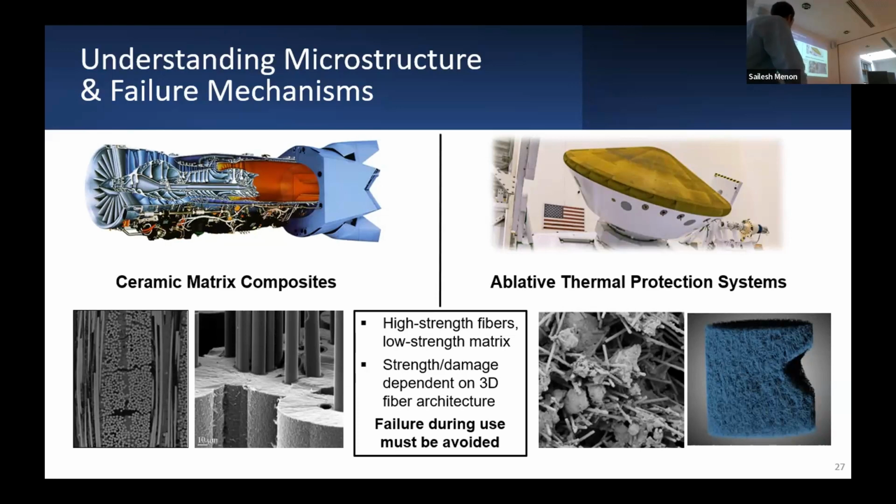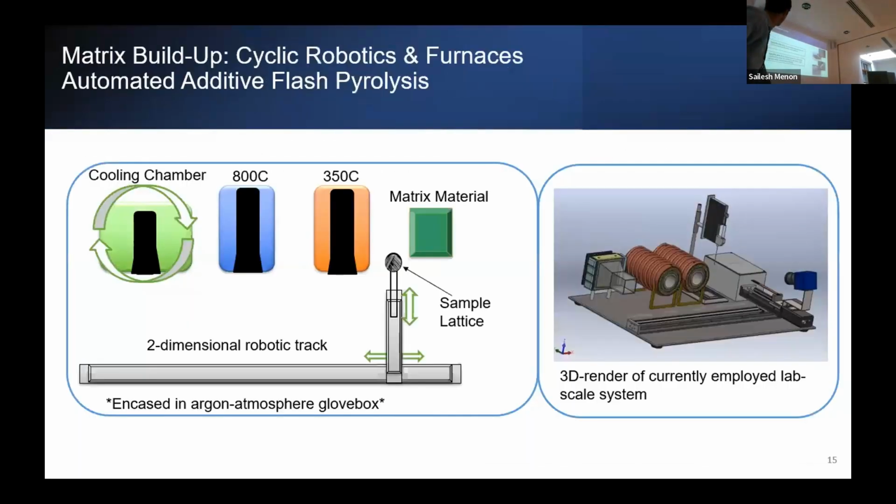Yeah, so I think one of the really important pieces is controlling impurities in the process. When we were initially doing the furnace work, the sample stage was originally copper, just because it was easy to manipulate so that it was lined up right. But we ended up with little bits of copper in the layer at the submicron level, which was a big problem. We'd see it under SEM.